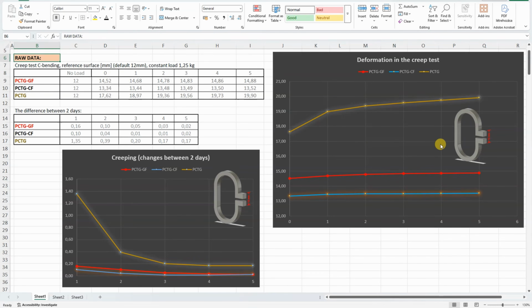On this graph we can see the distance between two reference surfaces, and we can see quite a lot of deformation on the no fiber version of PCTG, and then glass fiber and the smallest deformation on the carbon fiber version. Now the creeping is the difference between 2 days, and that's presented on the second graph, and we can see significantly more creeping on the no fiber version, and the creeping on glass and carbon fibers is very similar.